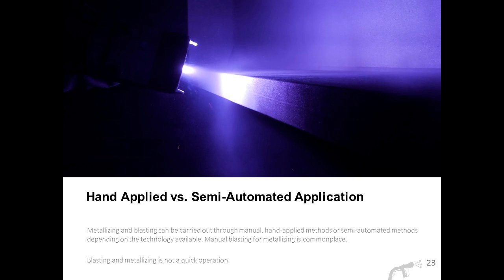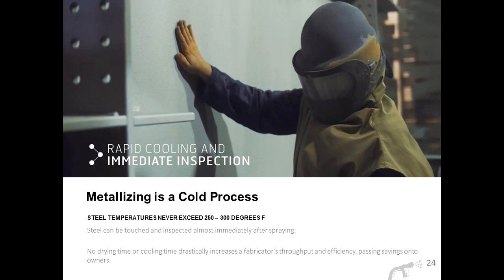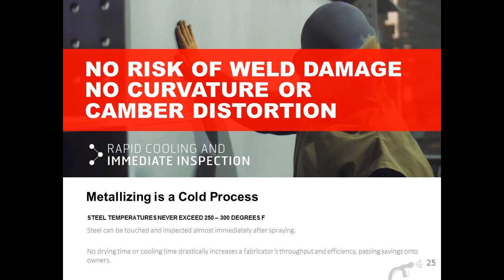The only counter to that, I would say, is because it's a cold process and it's not a coating like paint, you don't have to wait for anything to dry or cool or cure. Basically, once that zinc solidifies on the steel, you can touch by hand and inspect it immediately. That cuts down on the schedule and allows us to get a lot of girders through the shop quite quickly. Again, it's a cold process, which we talked about. The steel never exceeds 250 to 300 degrees. But what's also important to mention here is that there's no risk of weld damage or curvature or camber distortion that you can sometimes find when galvanizing.